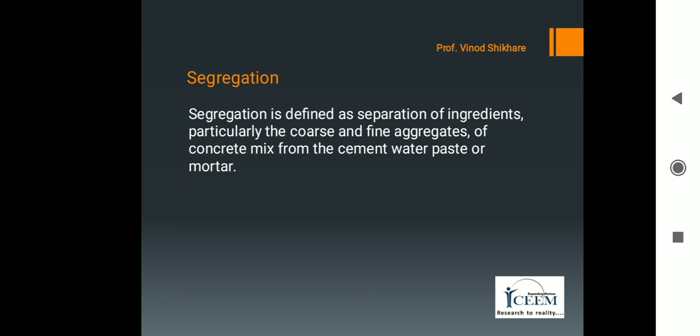It is also one of the most important factors affecting the segregation of concrete. Then over-compaction of concrete and a lesser quantity of cement, which lead to a harsh and less cohesive mix. Other factors are a very large maximum size of aggregates, complicated formwork with sharp corners, too much vibration, too long a transporting method of concrete, and leakage of water through formworks.